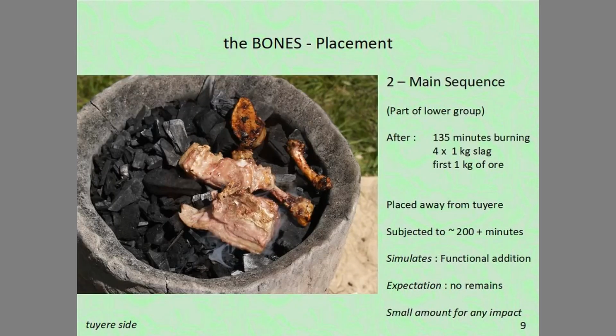After some discussion, it was decided to change the original plan and make not 2, but 3 additions of bone. The second addition was made partway through the main smelting sequence. At this point, the furnace had been burning for 135 minutes. There had been 4 kilos of iron-rich tap slag added to promote formation of the slag bowl, plus 1 kilo of ore. You can see that the bones have been placed away from the tuyere side of the furnace.